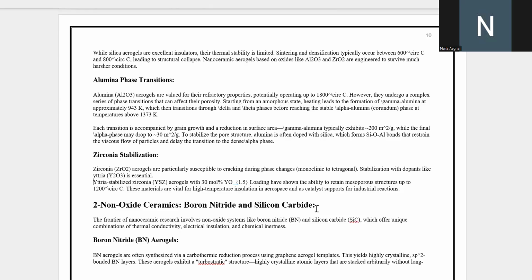This yttria stabilizes zirconia. It's like giving the material a flexible skeleton, locking it into a stable crystal form that doesn't change violently with temperature, preventing cracks. In short, alumina and zirconia aerogels are the advanced heat-resistant upgrades to silica. Scientists engineer them with special dopants, like silica for alumina and yttria for zirconia, to overcome their natural tendency to collapse or crack, making them perfect for the most demanding insulation jobs on Earth and in space.